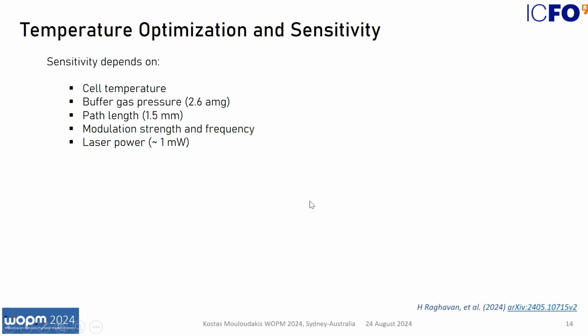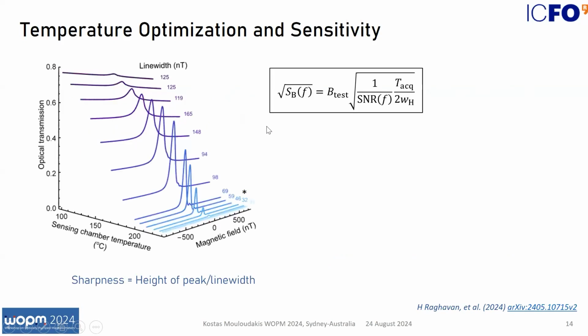Finally, we use these cells to perform magnetometry. There are certain parameters that affect the magnetic sensitivity. Some of them are related to the fabrication of the vapor cell, like the buffer gas and the path length. Some others need to be externally optimized, like the cell temperature or the modulation strength and modulation frequency. To optimize first the temperature, we look at the zero field resonance as we scan the transverse magnetic field and at different temperatures. We look at the sharpness, which is the height of the peak over the linewidth, and we try to see where the sharpness is maximized. And in our case, it was around 200 degrees.